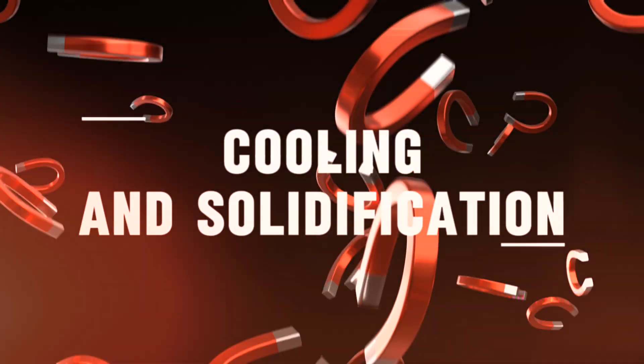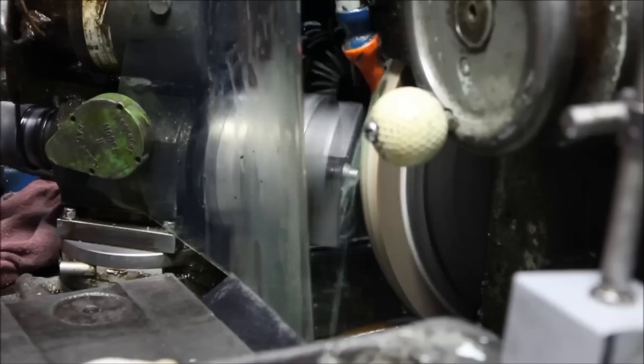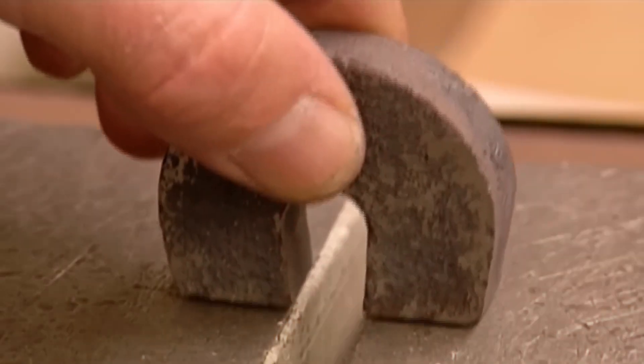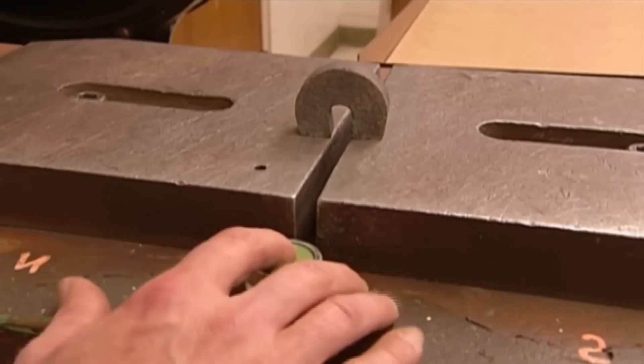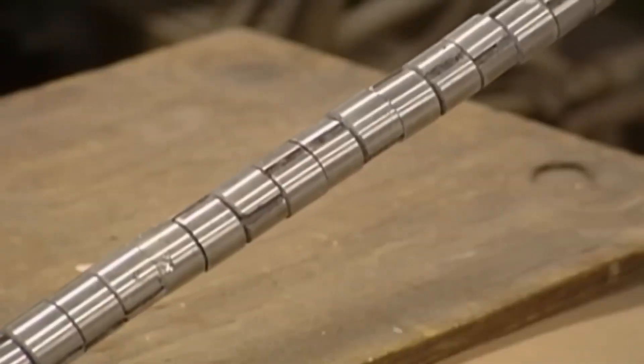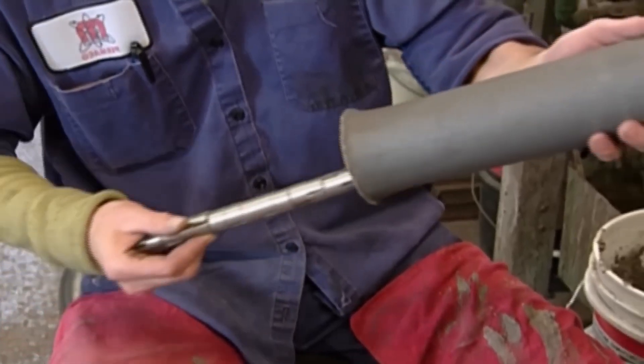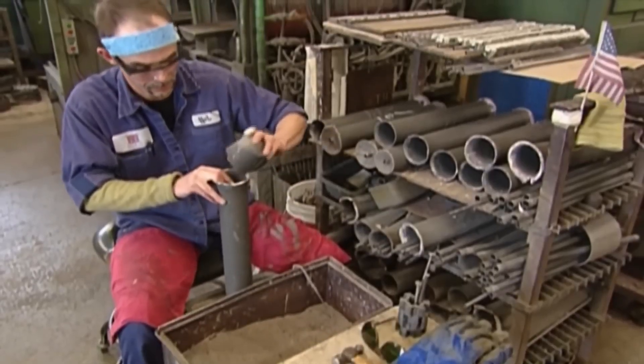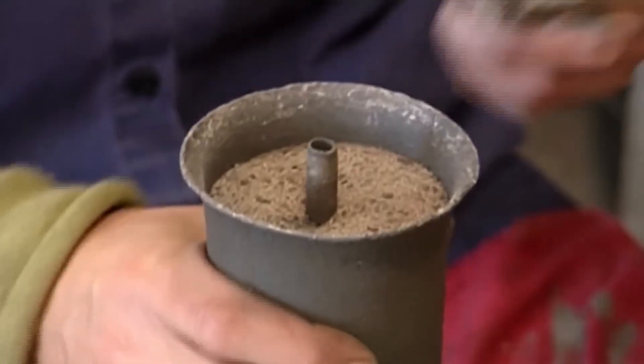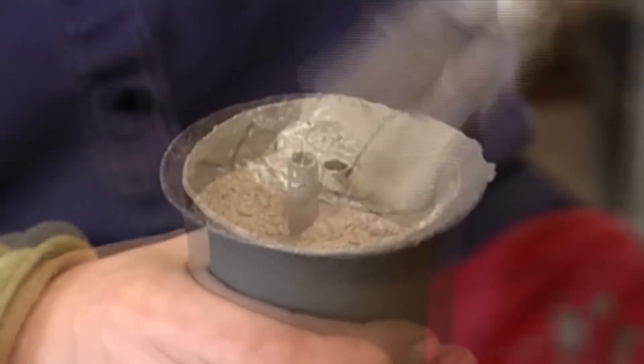Preparing for Heat Treatment: The solid metal shapes look like magnets, but they are not magnetic yet. Workers collect the cooled pieces by shoveling everything into a bin and pulling the usable shapes out with a magnet. Once sorted, the pieces are prepared for heat treatment. For example, ring-shaped magnets are threaded onto a copper pipe. This pipe is then placed inside a larger tube, and the empty spaces are filled with silica sand to hold the rings in place, ensuring they will not shift or warp when heated. Both ends of the tube are sealed with concrete, leaving just enough of the copper pipe exposed so it can conduct heat properly. It looks more like construction work than precision science, but each step has a purpose.